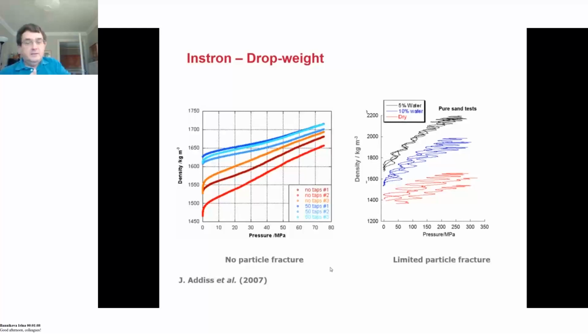Then we repeated those experiments using sand to which we had added by volume different amounts of water, either dry sand, 10% water, or 5% water. And here we see the effects of doing that experiment on the drop weight. What we see again is an increase in density. You can see that the dry sand's gone from 1400 to around about 1600, hasn't gone quite as dense. You can see adding the water to the system has provided some lubrication to the system, so you get a good deal more densification under these drop weight conditions.